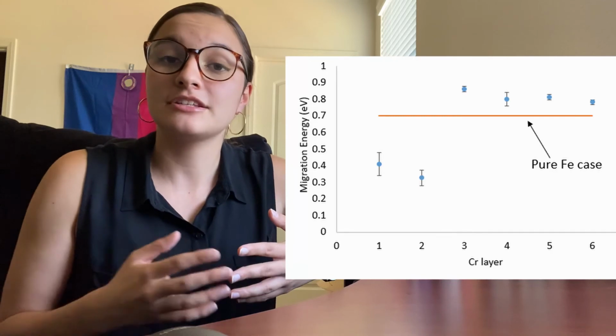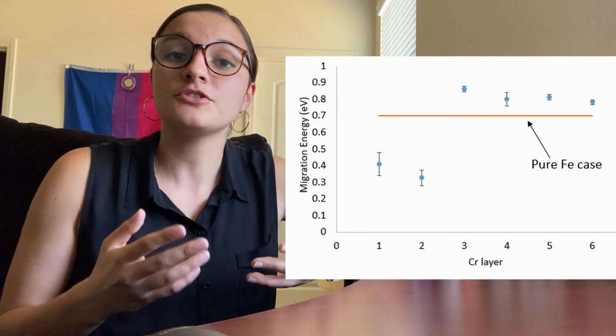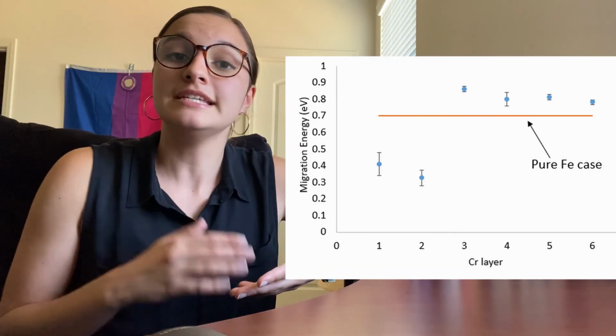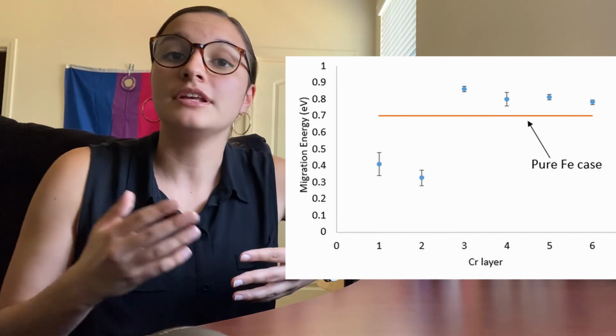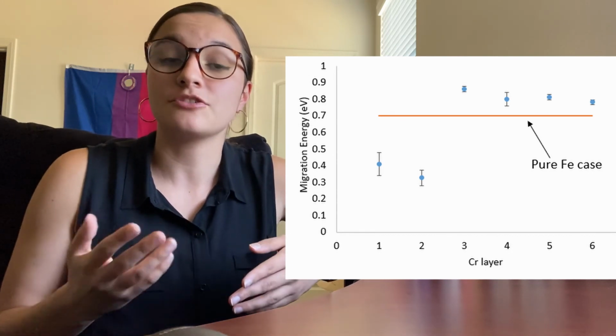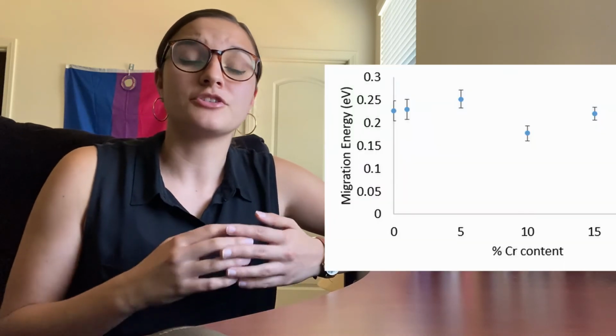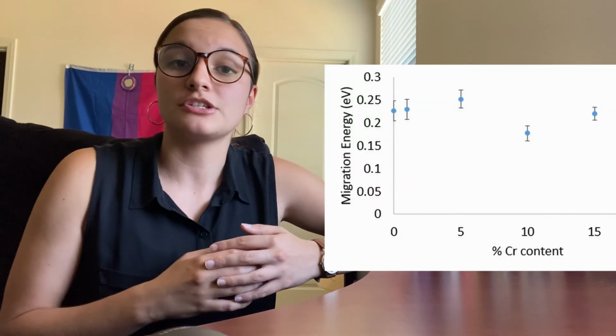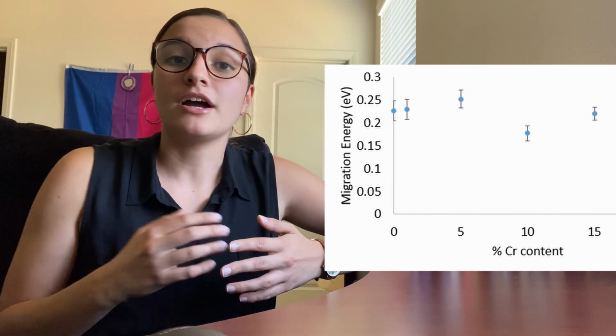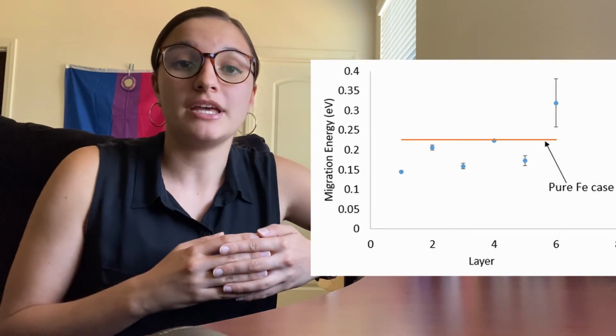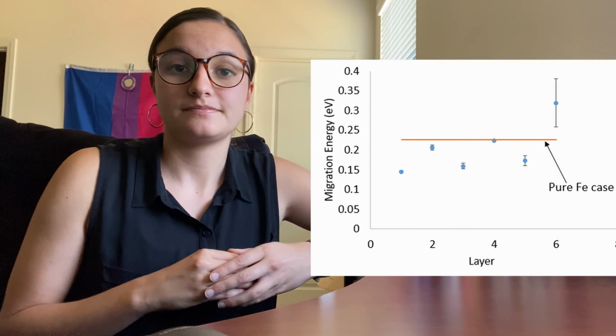Meanwhile, in the layer cases for 110, we noticed that the first two surface layers would cause a decrease in migration energy, while the layers in the bulk structure caused an increase in migration energy. For the 110 surface, we noticed that there was more of a plateau with the random concentration of chromium cases. Meanwhile, we saw an interesting oscillatory behavior in the layer cases.